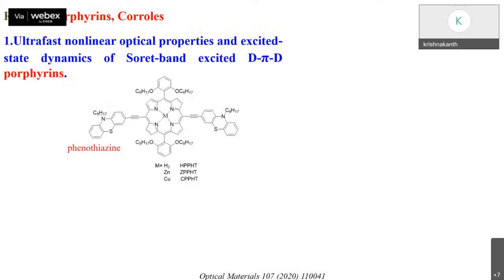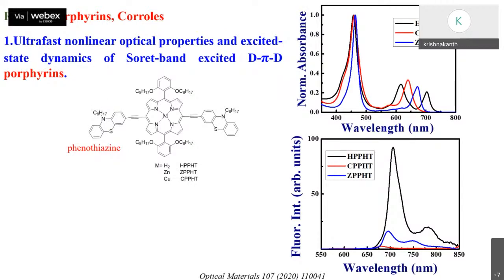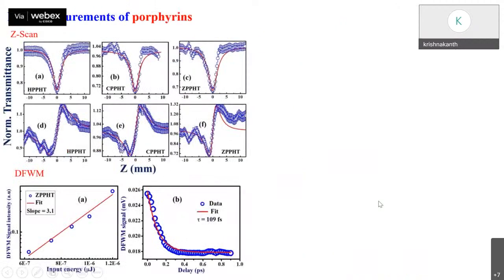So I'll quickly go to my results. We have studied these NLO properties in porphyrins and corroles, two systems. This is a porphyrin which I studied. This porphyrin ring is with phenothiazine, and the center is doped with H2, zinc and copper. These are the steady state measurements, absorption and emission. These are the structural parameters, and this is the NLO data, the Z-scan curves at 800 nanometer and four-wave mixing at 800 nanometer.